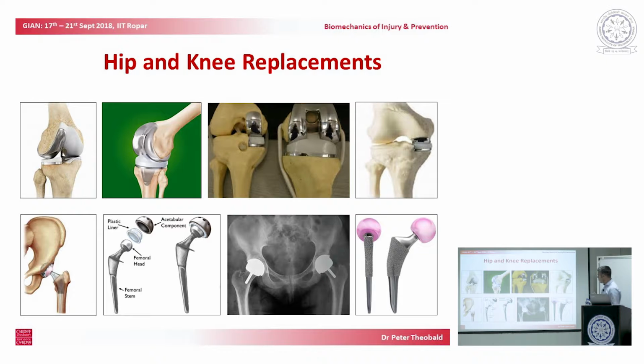And indeed, the failure of metal-on-metal implants wasn't really their rate of wear. Patients weren't complaining overly about these implants failing prematurely. It was the consequence of the wear particles they generated. And they were trapped around the soft tissue. The synovial membrane around the joint trapped those metallic ions, and they became known to be harmful to the body.